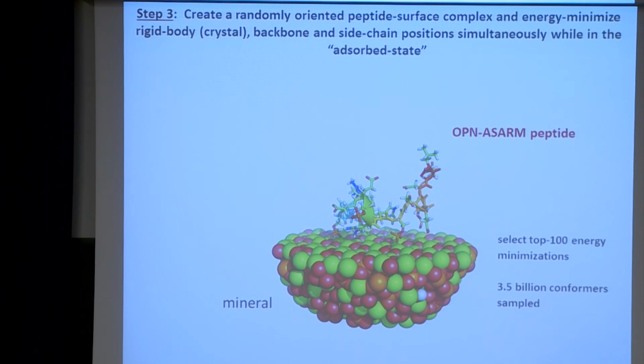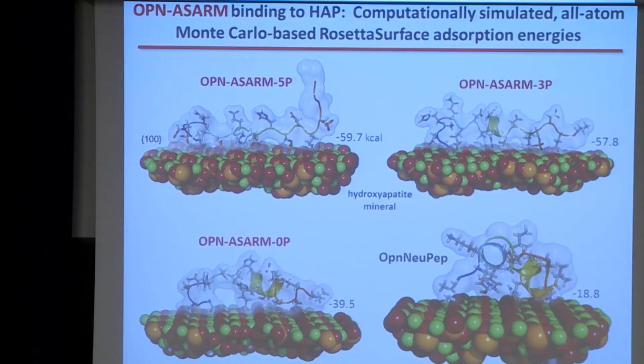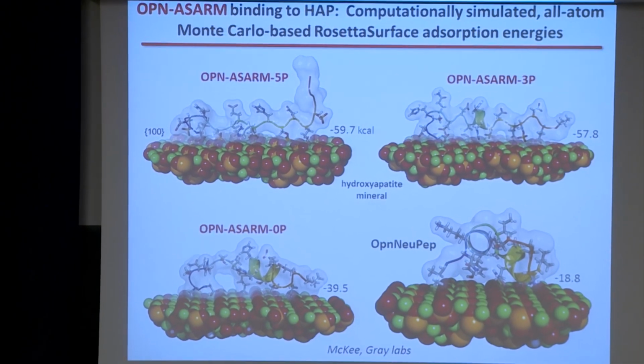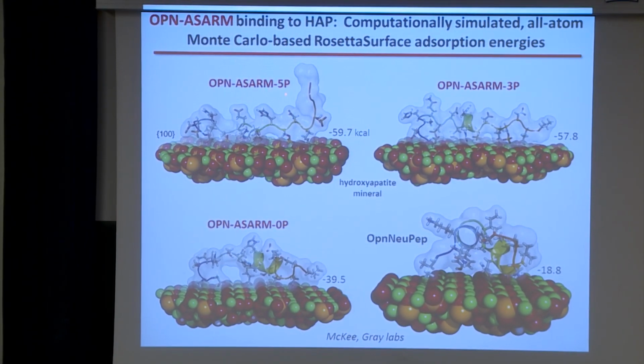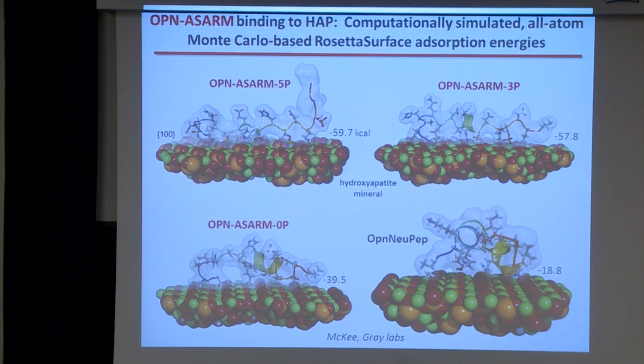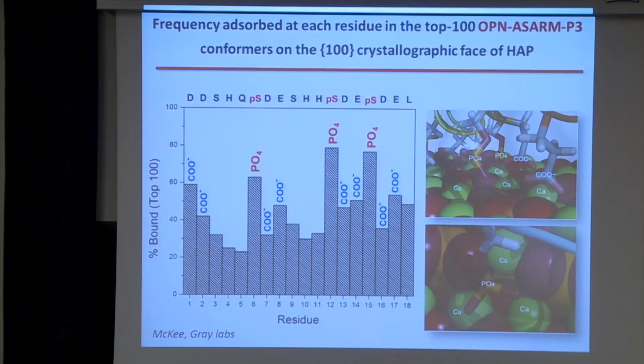And Professor Coombs, I know we have to pay more attention to the hydrated state and the carbonate substitutions, and the HPO4 groups. But we started with hydroxyapatite and got some really good binding energies. You take the top 100 energy minimization conformers after sampling 3.5 billion, and you get the binding energies in Rosetta surface units. The highly phosphorylated peptides were the best binders compared to 3 phosphates, 0 phosphates. Here are the binding energies, and they often extended out along the surface lattice calciums like that. So that's what the modeling showed us, and it fit very nicely with the in vitro data.